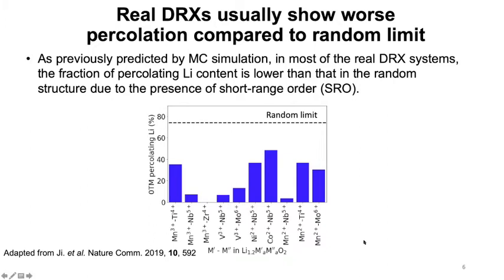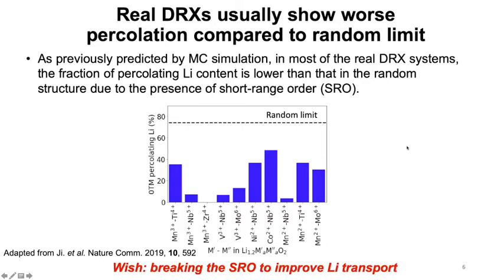However, in real systems, because of the presence of short-range order, the exact amount of percolating lithium is significantly reduced compared to that in the random limit. In other words, the short-range order will negatively influence the lithium transport property in DRX material. So we have a wish here. That is, if we can somehow break the short-range order in DRX material, we are expected to improve the lithium transport property. Okay, how can we achieve that?